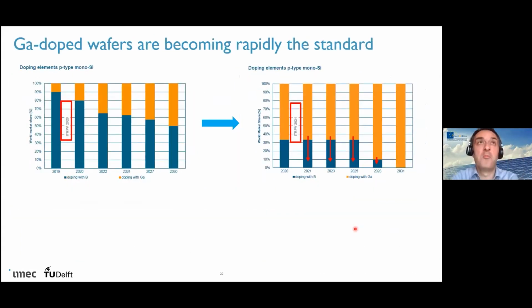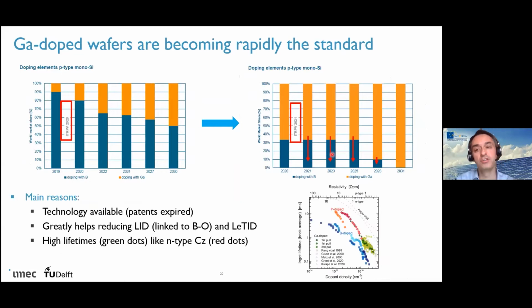Something else we see is that until now, most of the cells that were made were based on P-type wafers. And P-type wafers, traditionally for silicon, are boron doped. But the whole industry in recent years has been switching from boron doped wafers to gallium doped wafers, and the reason is that it really helps reduce so-called light induced degradation.